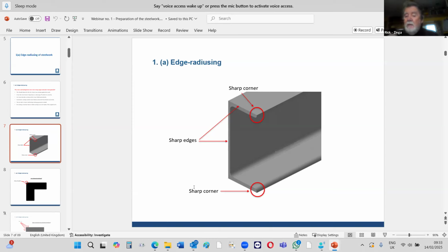Then just take an angle grinder with a sanding disc. Not a grinding disc, that makes a mess. You just take a sanding disc with something like a 40 grit or 36 grit disc, and run it down that edge, down that edge. It takes literally 20 seconds, and you have a nice radius. Internationally, they look at 2 millimeters or 3 millimeters. 2 millimeters is fine.